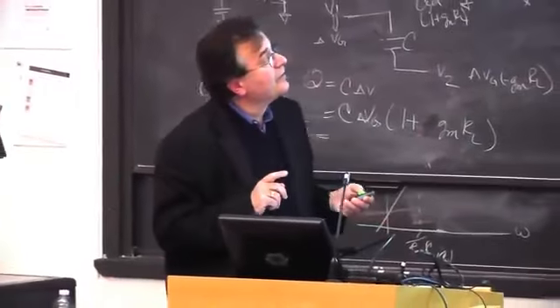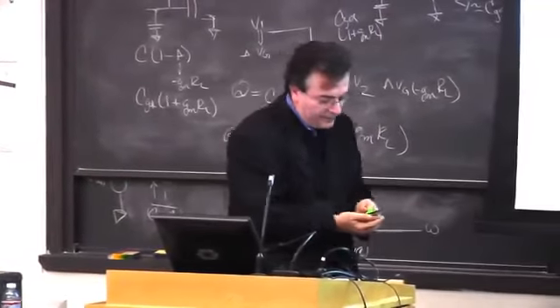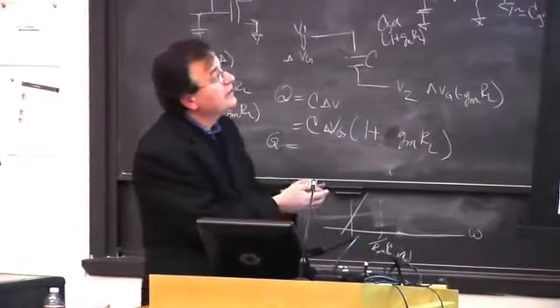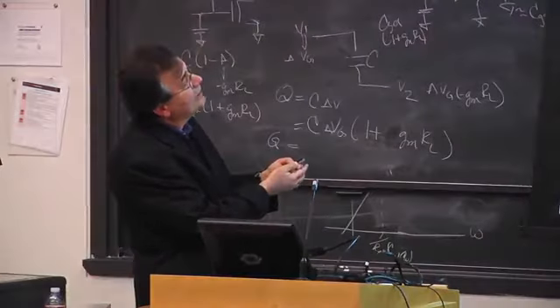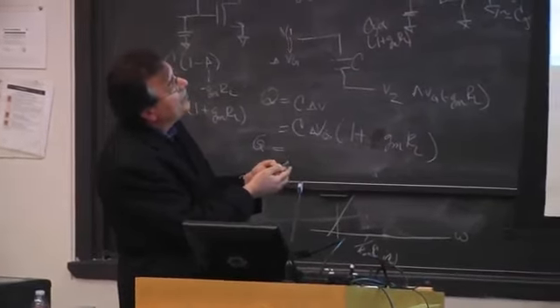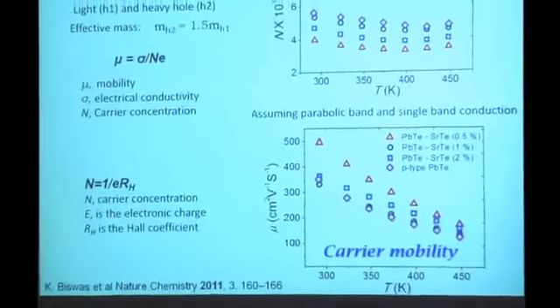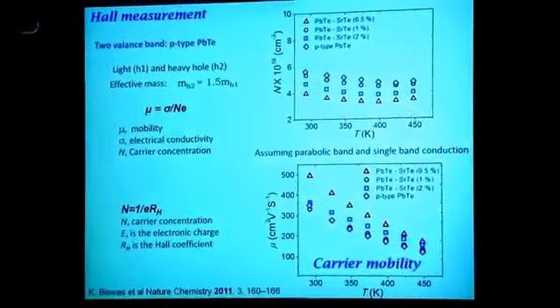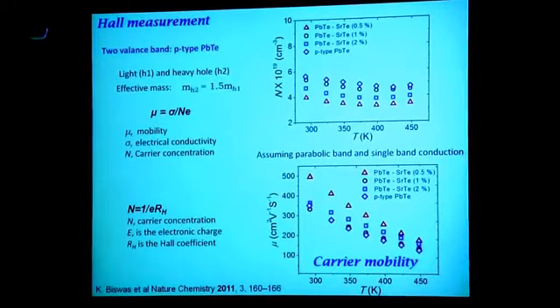And here's what we found. This was a very amazing result for us. We measured the carrier concentrations, and they were more or less between 4 and 6 times 10 to the 19th for this amount of sodium doping. And then we took samples that had the same carrier concentration and compared them to a sample that was pure lead telluride with the same carrier concentration, but no strontium.